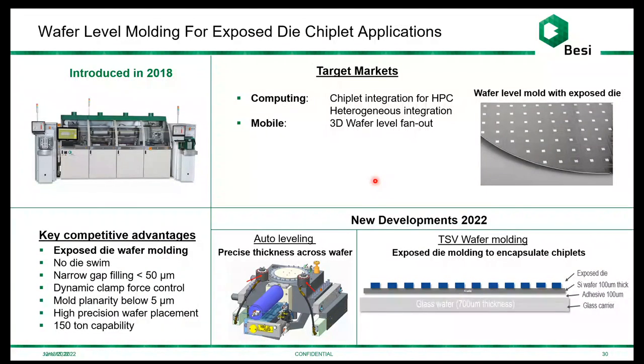And then for all these applications that require wafer level assembly, at the end of the day, we need a way to encapsulate the wafer. So for this, we are offering a wafer level molding system. What we do a little bit differently at Besi compared to what most people are used to is we employ transfer molding. And the benefit of transfer molding, especially for applications like hybrid bonded chiplets, is that you can do exposed die molding at the wafer level. So you can expose the backside of whatever you just mounted to the wafer during the molding process. So this is something that's also available and being used in R&D.